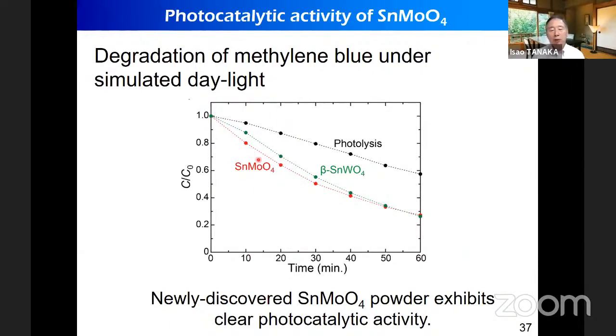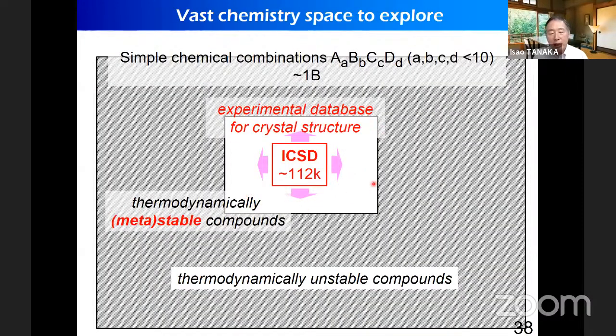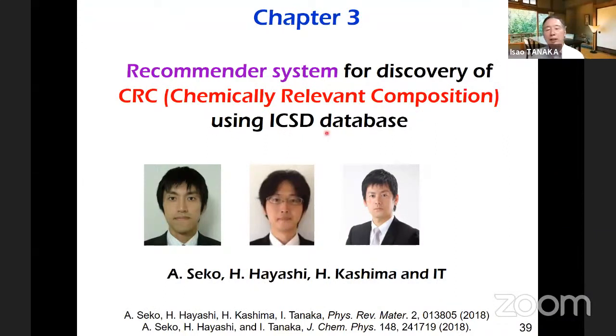And this is a new compound, tin molybdenum oxide, in comparison with the already reported tin tungsten oxide. And our new material shows almost the same or slightly better performance than this already reported tungsten oxide. So in that way, we have confirmed the presence of a new compound which is suitable for photocatalytic application. So we entered this region and we found just one, but probably this is much, much wider. And we are interested in what is going on there. So that is further motivation for the third part.